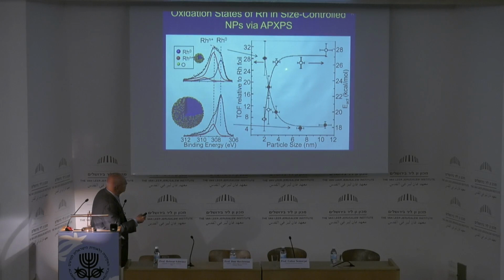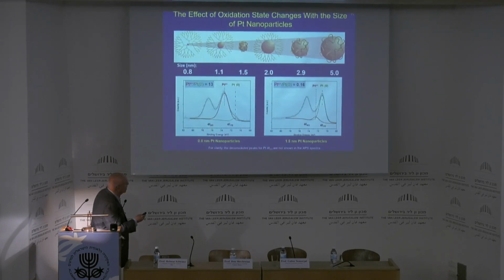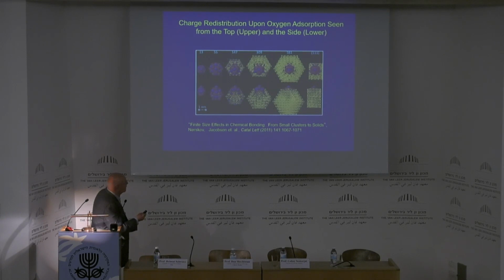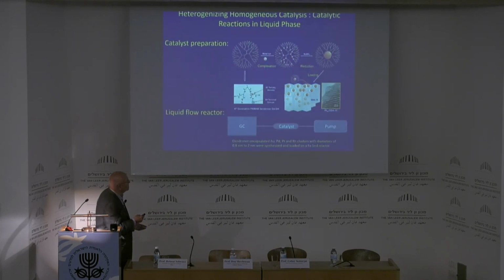if you take a gold nanoparticle, a big one, and this is the size of this nanoparticle, the red part is where the oxidized gold forms. By the time you go to about 5 nanometers, and you should remember that 1 nanometer is roughly 40 atoms, you go to that one, the whole gold nanoparticles becomes gold 2 plus and 4 plus. And so when you go to these small nanoparticles, then the oxidation state changes. Now, this got us into heterogenizing homogeneous catalysis.